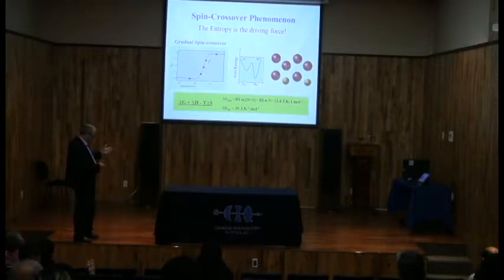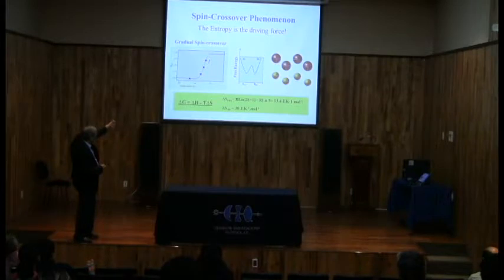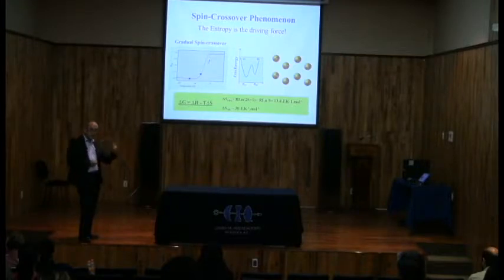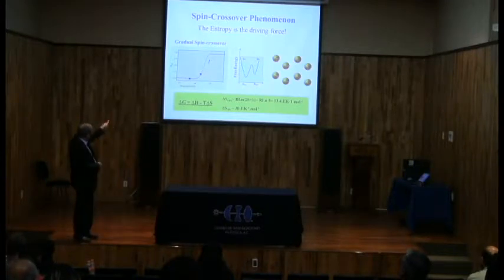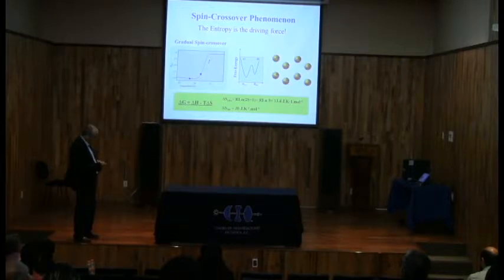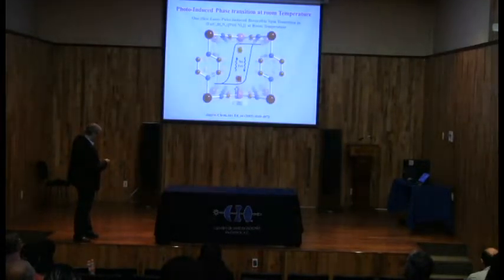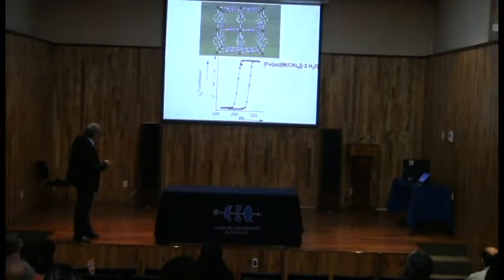If you cool your system, you will destabilize the double potential on the other side, and then you switch to the other part. So just by temperature, through the entropy, you can have your switching, and we say that the molecular switching is driven by the entropy change of the system. This explains the mechanism of the switching.